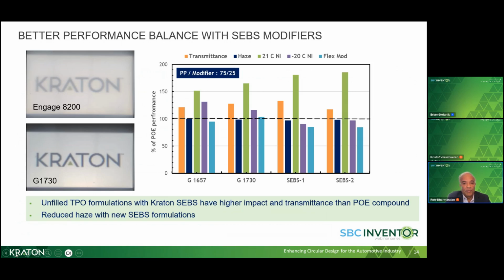So we measure transmittance and haze using 3 millimeter injection molded samples. And as you can see here with our new SEBS1 and SEBS2, we have fairly high transmittance and also low haze, which is what Brian alluded to. The best combination, having high transmittance and a certain minimum level of haze, but lower would be better. Our G1730 commercial product also gives us the same combination.